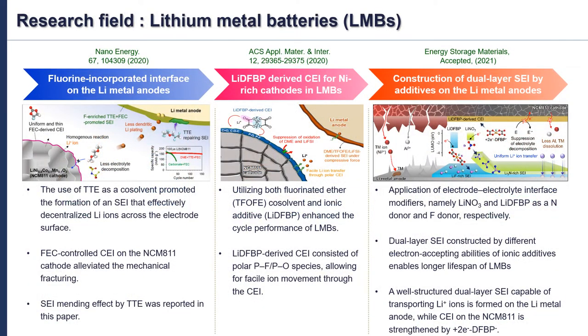To enhance the energy density of batteries, lithium metal has been considered as a promising anode material. However, its high reactivity with electrolyte causes many problems, such as lithium dendrite and thermal runaway. To solve it, we have introduced fluorinated ethers, such as TTE and TFOFE, as co-solvent, to form a mechanically robust lithium fluoride-based SEI on the anode. Specifically, TTE effectively mends the SEI cracking during repeated cycling, which enables the long-term cyclability of lithium metal batteries.